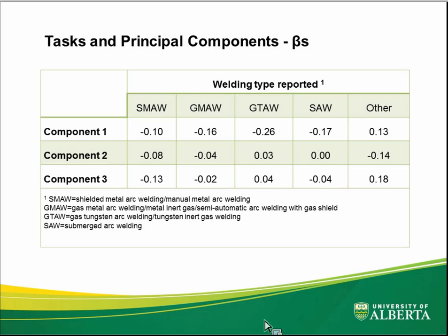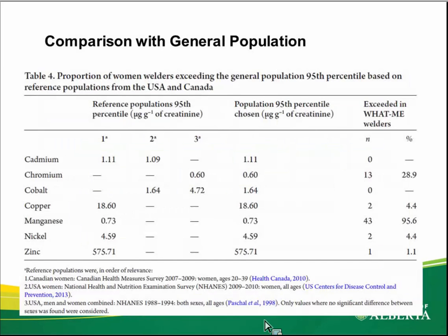We looked at whether the component scores were associated with the types of welding that these women were doing. And again, we didn't adjust for smoking and age, but we also didn't see any significant associations between these composite scores and the types of welding that was happening. And I can tell you that we did look at other things like base metals that they were using, and we still didn't see any clear patterns jumping out in this small group of women.